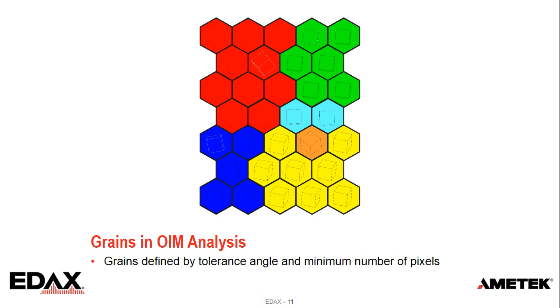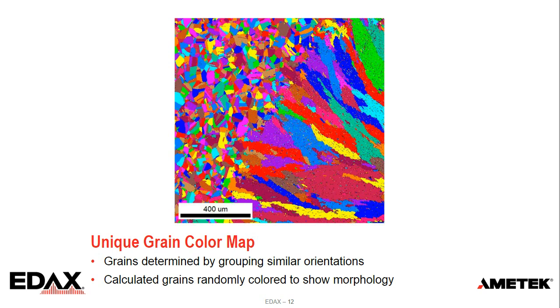Once we've determined the grains, we can then randomly color them. We call this a unique grain color map or just a grain map. The colors are such that no two adjacent grains have the same color, so it really shows the morphology, the size and shape of the grains. And again, we can see that the weld grains are a much different shape than the base metal.